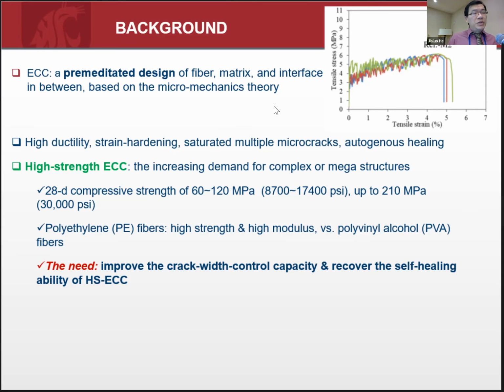Now here we're using a high strength PE fiber, or polyethylene fiber. And this kind of fiber can help improve the strength because the fibers are different. The challenge though is that PE fiber is not hydrophilic, so it doesn't bond well with the cementitious matrix. What happens then? For traditional ECC, your maximum crack width will be around 100 microns. For PE ECC, you end up with 150 microns. So in that case, it's harder for it to heal itself when it's cracked. So in order to improve the crack width control and also enable better self-healing, we need some creative solutions.